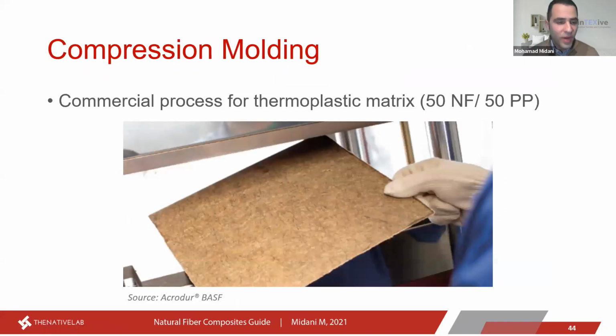Okay, so for the composite manufacturing techniques, again, the most important commercial technique is compression molding. And as I said, the material that is widely used in the composite industry is natural fiber thermoplastic nonwoven with 50% natural fiber and 50% polypropylene in a nonwoven structure. And they're mainly compression molded. It's cost effective, especially with thermoplastics, the industry is interested in this because of its short production cycle. So you can easily compress, consolidate, and then solidify quickly. So that's why it can be produced as mass production.